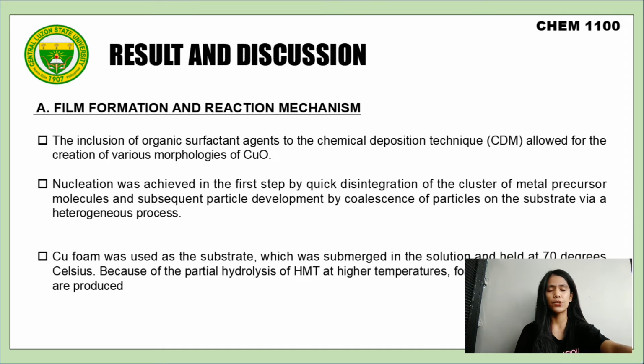The slide was the film formation and reaction mechanism. The inclusion of organic surfactant agents in the chemical deposition technique, or CDM, allowed for the creation of various morphologies of copper oxide. The solid phase in CDM is created by dividing a supersaturated solution into two stages once it has reached saturation. Nucleation was achieved in the first step by quick disintegration of the cluster of metal precursor molecules, and subsequent particle development by coalescence of particles on the substrate via a heterogeneous process.